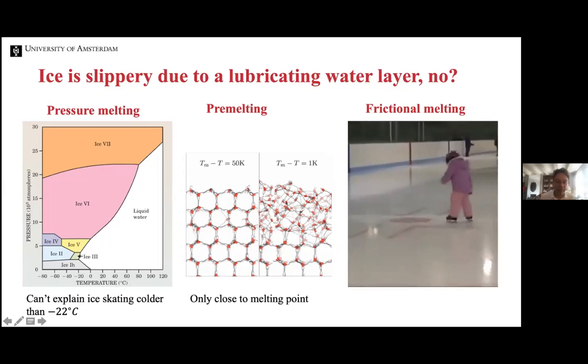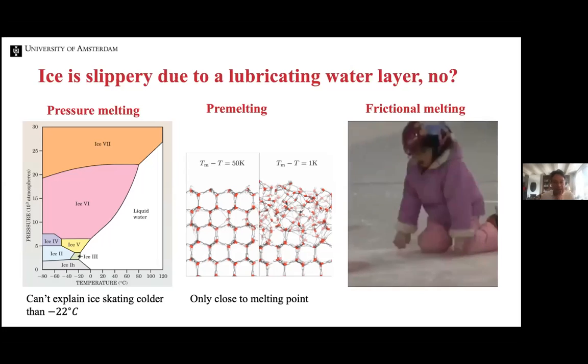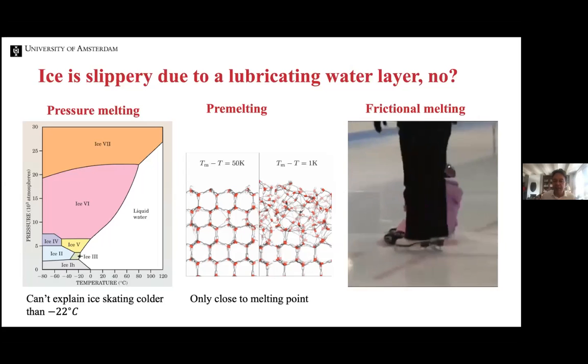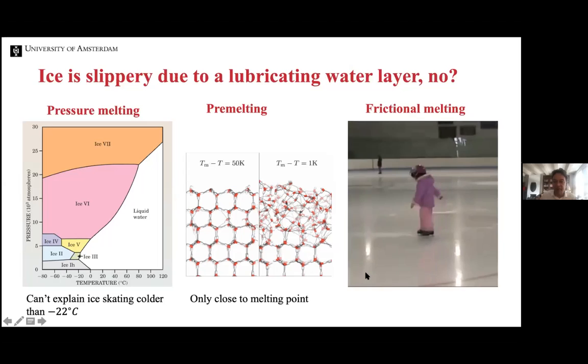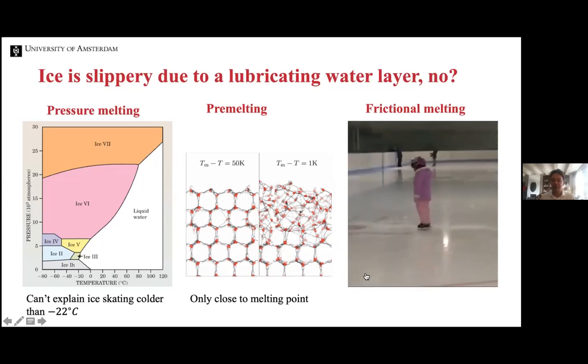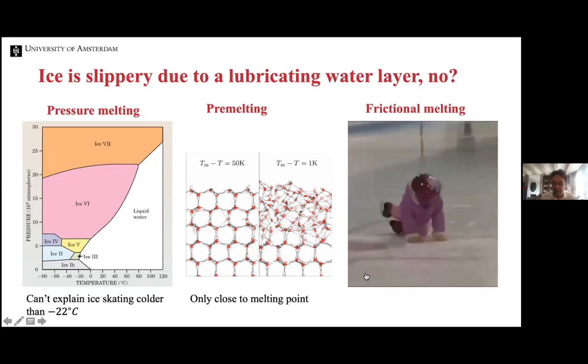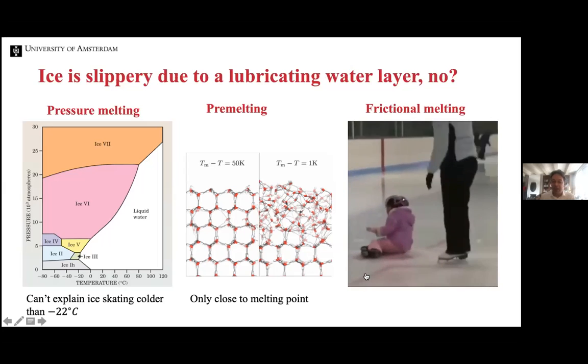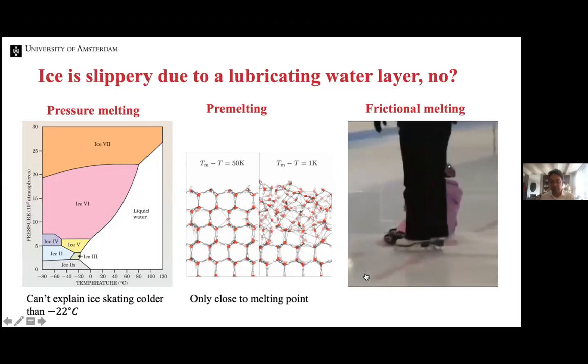The most accepted explanation, probably, is that the skating itself heats up the ice because of friction generating heat, and this frictional melting then creates the water layer that allows you to skate on the ice. But if you look carefully at this movie, this little child actually doesn't go very fast, and by the time she, I think it's a she, falls, she's actually standing still. Yeah, and so frictional melting is perhaps important for high-speed ice skating, but for explaining the slipperiness of ice, I don't think it's the correct explanation. Yeah, because it can't explain low velocity skating.